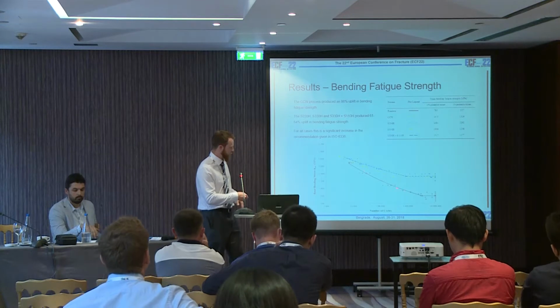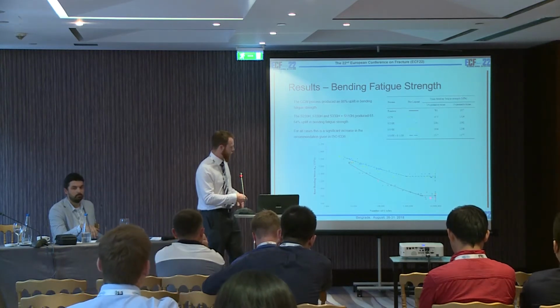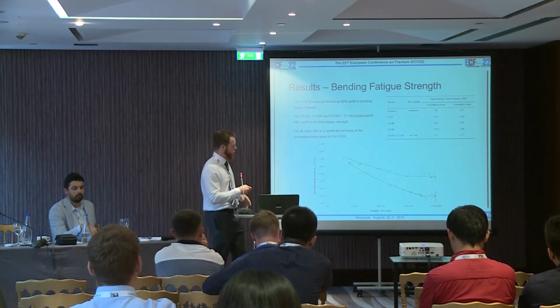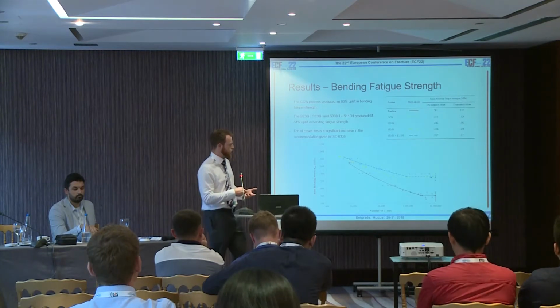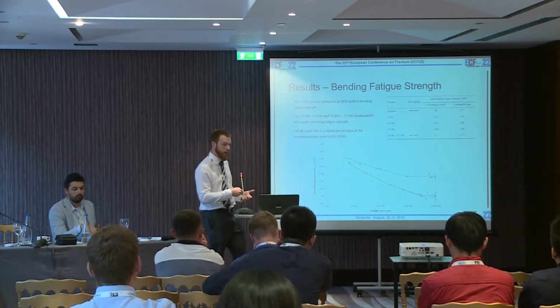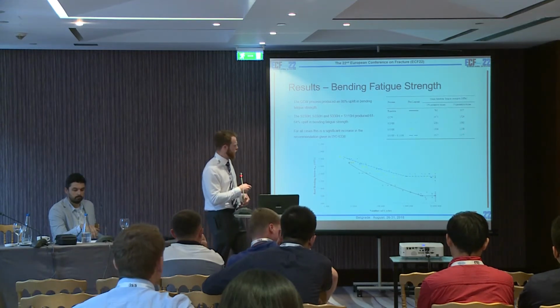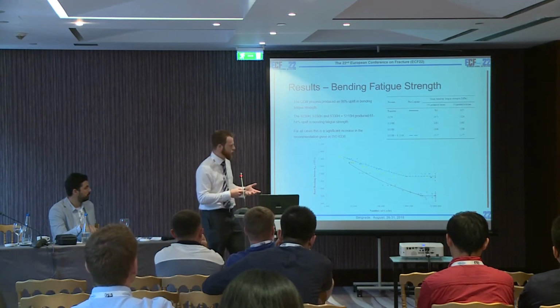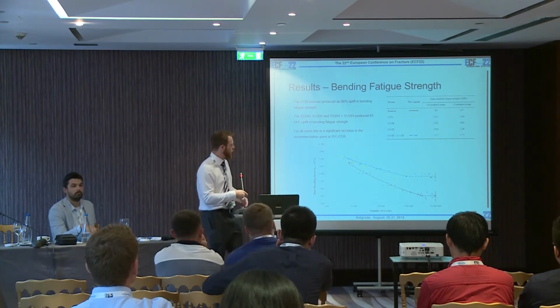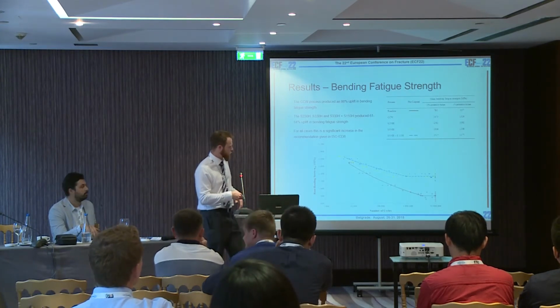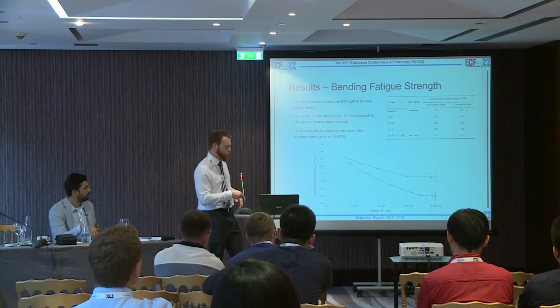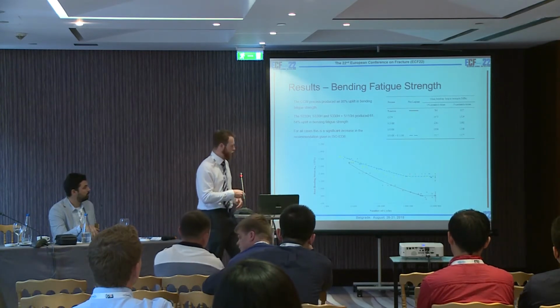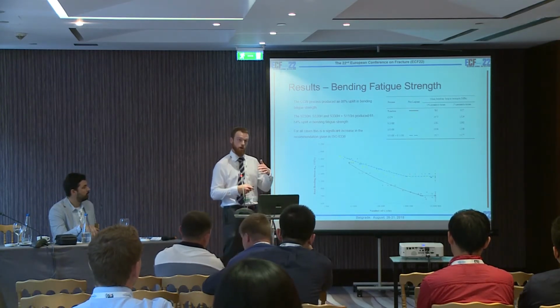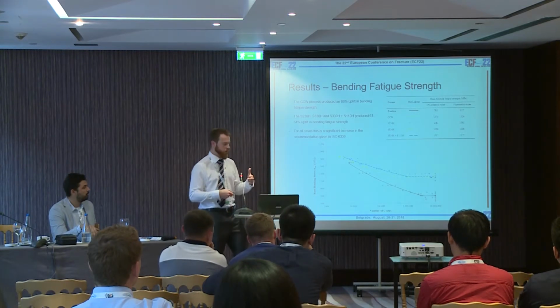So the red line again is the baseline steel. I should note the test method that you use for this type of testing gives you a 50% probability of failure. You can calculate the 1% probability of failure based on the standard deviation, which isn't in this table, but it is in the paper, so you should be able to find that there. Overall, we saw approximately an 86% uplift in bending fatigue strength for the condition cut wire process, so a really significant increase in the bending fatigue strength.